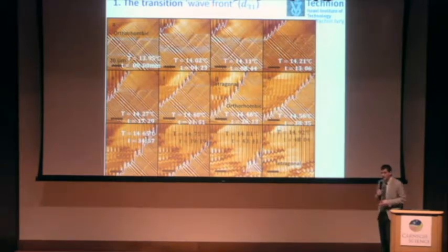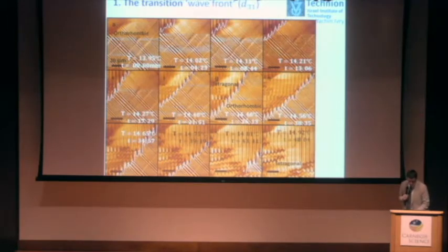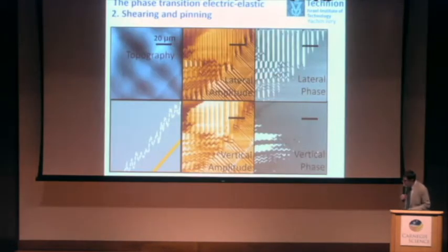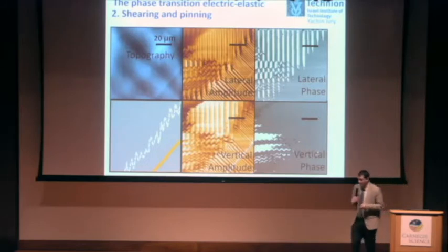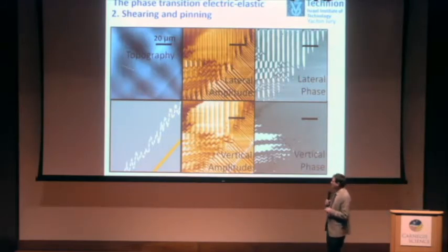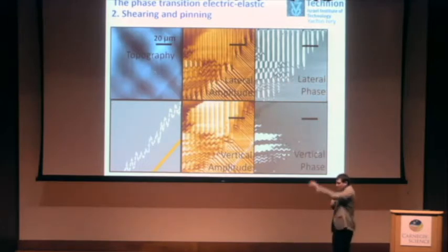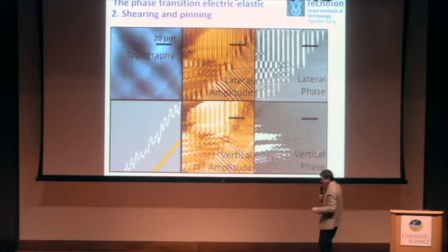If we take into account Elisabeth Soergel's analysis, we believe that these are orthorhombic leftovers, but we cannot be sure. Anyways, these are different domains. So I showed you only one type of the PFM image, but of course you can look at the topography, and you could look at the D33 and the D31 to get the 3D structure of the entire domains.